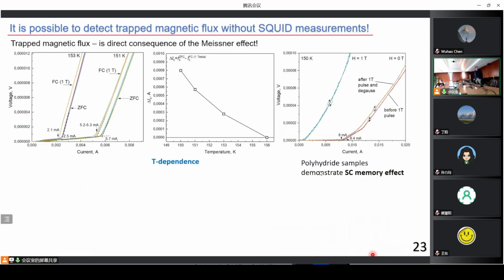It's 7.6 milliamperes instead of 8.4 milliamperes. Okay, we repeated this experiment in a different manner. We cooled the sample in magnetic field. It's a field cooling in 1 Tesla. We cooled the sample firstly without any field and measured the critical current at different temperatures. And we repeated the experiment several times, so that's why you see several curves here. They reproduce each other very well. It's not a problem to reproduce it.